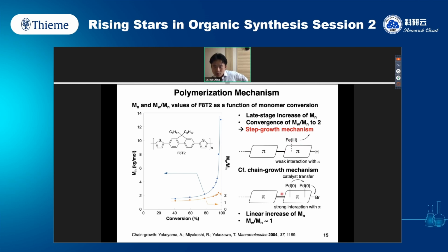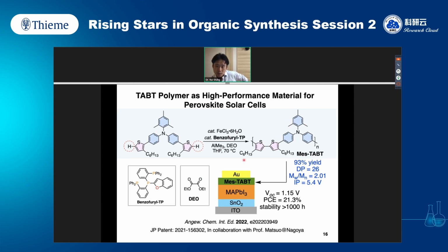This is in contrast with the chain growth mechanism, such as when we use palladium. The palladium always sticks to the end of the polymer, so the polymerization goes through a chain growth mechanism. One donor polymer we made by this iron-catalyzed CH polycondensation is a new polymer. We found it's an excellent material as a hole transporting material for perovskite solar cells. We achieved a 21.3% power conversion efficiency, and especially the VOC is very high because of the very good energy level matching of this polymer with the perovskite material.